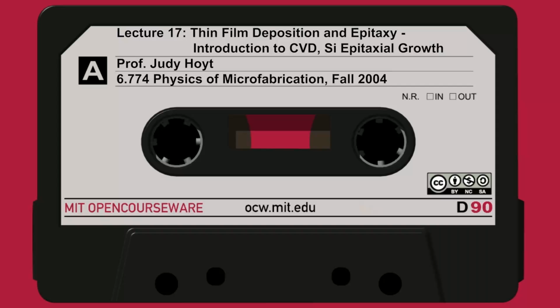Modern epitaxy often operates, however, if people are growing silicon germanium and other materials that need to be grown at lower temperatures like 800 or so, or 700, often operates in this regime now, these days, where you're in the exponential regime. So controlling the temperature becomes extremely important in order to get good growth rate control.